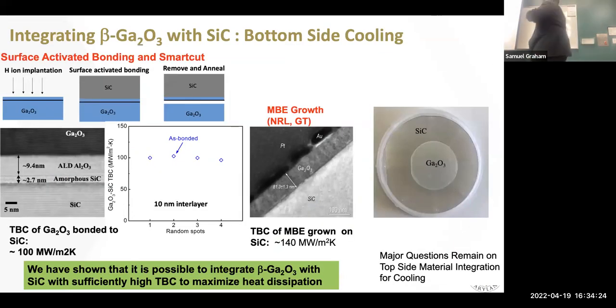So let's go back to our favorite way of putting these together. Remember I said if I have really thin gallium oxide, then I can put it on a high thermal conductivity substrate. I don't need diamond. What we're doing here is gallium oxide. This one used a very thin layer of aluminum oxide to help with the bonding. The ion irradiation caused an amorphous silicon carbide layer. So you can see a continuous theme here: I have something that turns into an amorphous layer, and I put this on silicon carbide.